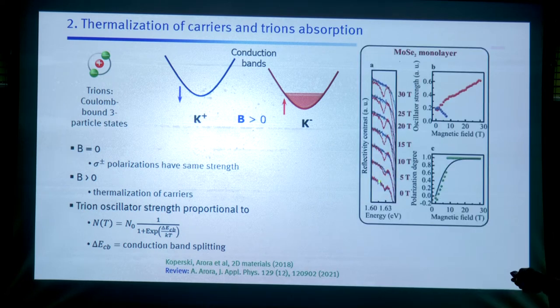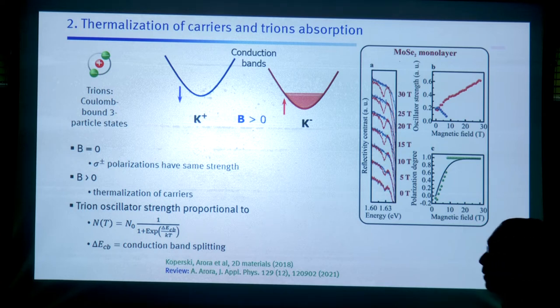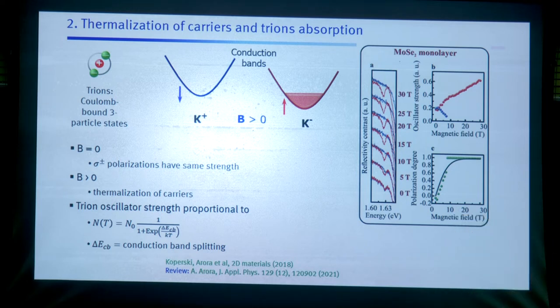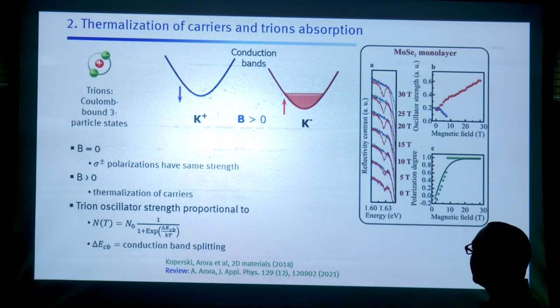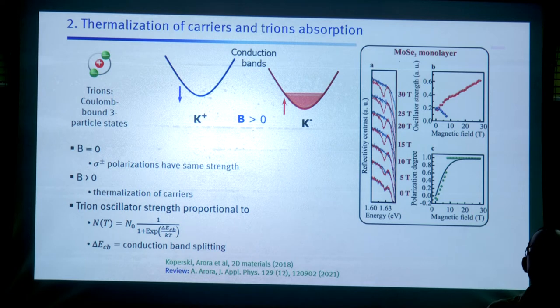At zero Tesla magnetic field, there is this trion in MoSe2. This is MoSe2, molybdenum diselenide monolayer. The blue and red lines, which are the two circular polarizations, look the same. But once you increase the magnetic field, there is a strong polarization because the carriers are shifting to the other side. So this is the valley polarization of trions, but this is magnetic field induced. We can use the magnetic field to tune the population of carriers between two valleys.